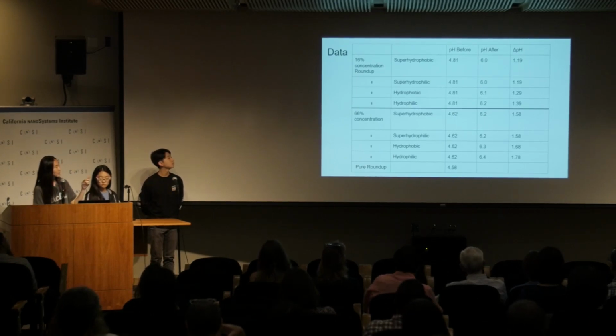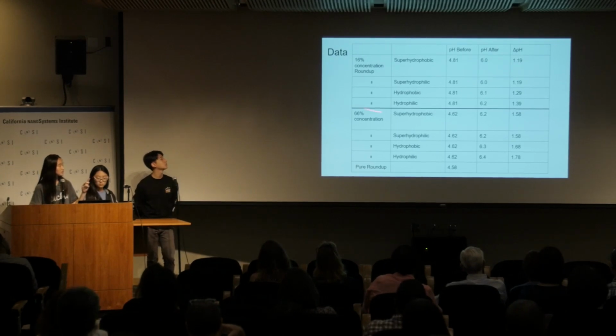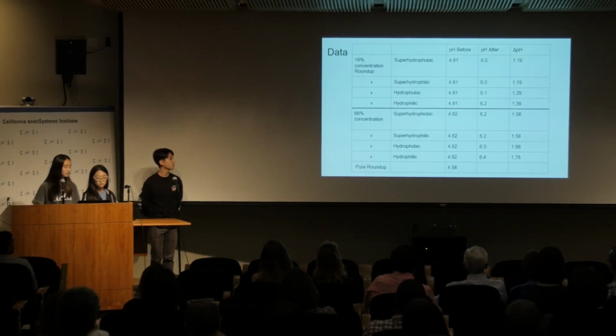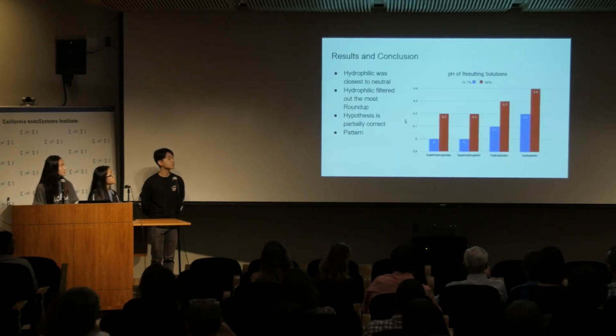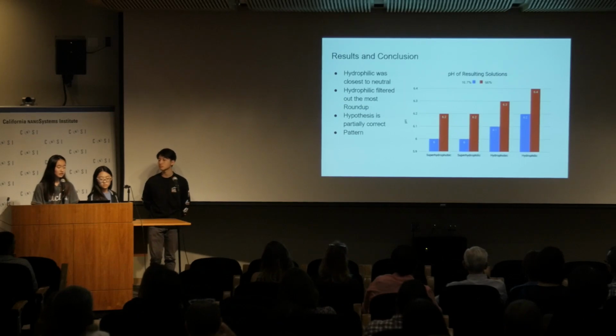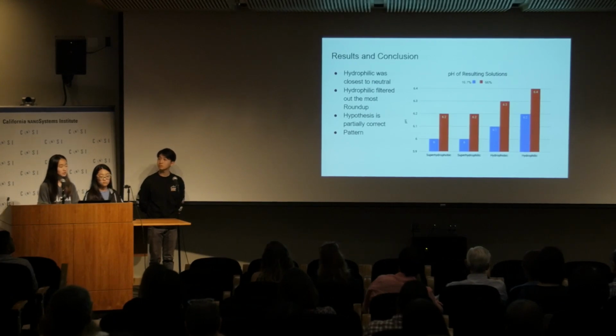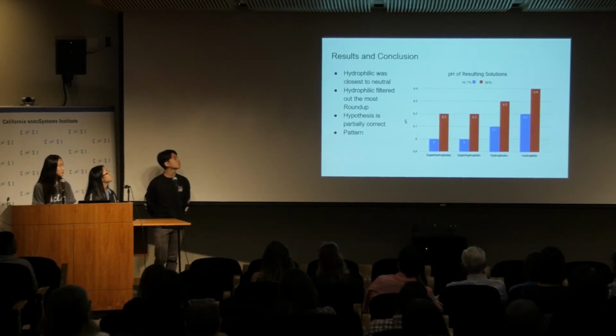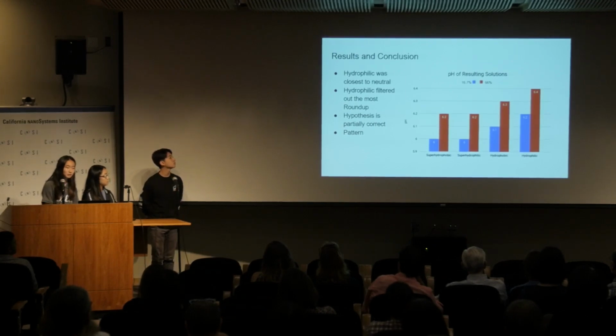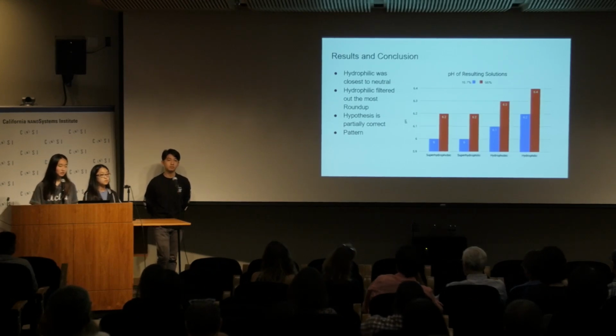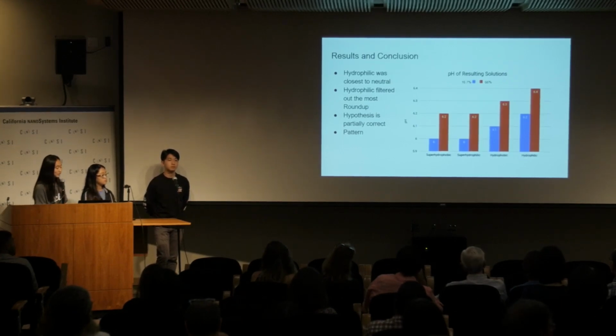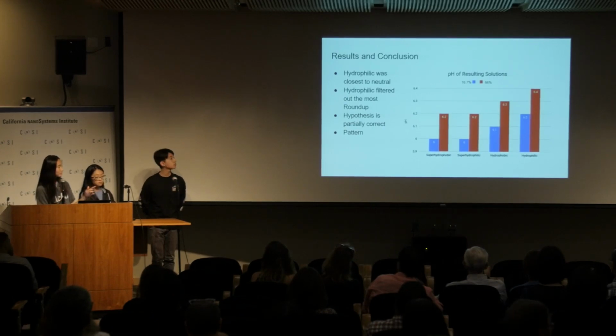And we can see here that the hydrophilic filter was consistently the most efficient for both concentrations. So we came to a conclusion that the filtered solution for the hydrophilic filter was closest to neutral pH, which is 7, and it filtered out the most Roundup, which shows that our hypothesis was only partially correct because we hypothesized that the hydrophilic filter with nanoparticles would be the most efficient. And from this bar graph of the pH of resulting solutions, we can see that there's a pattern. So the hydrophilic was consistently the most efficient for both concentrations.